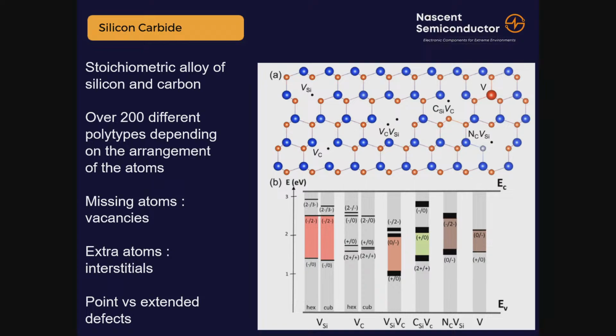This is why silicon carbide MOSFETs are not as good as they should be. They've got all kinds of problems like threshold voltage instability, carbon interstitials. Some good work came out of Japan a few years ago on this. We also end up with a situation of point versus extended defect. So you've got VC, VSi and CSi-VC. Okay, so you've got a carbon silicon divacancy and a silicon carbon site with a carbon vacancy next to it.